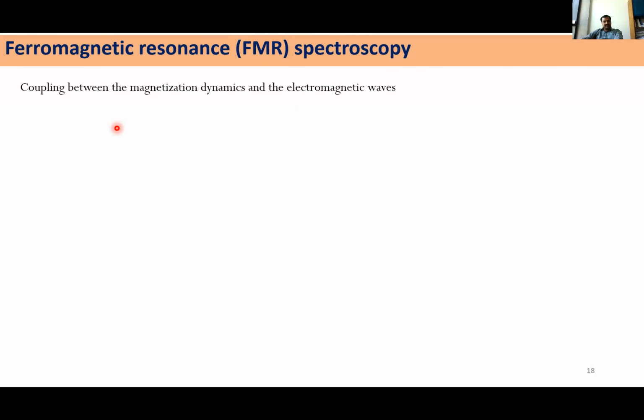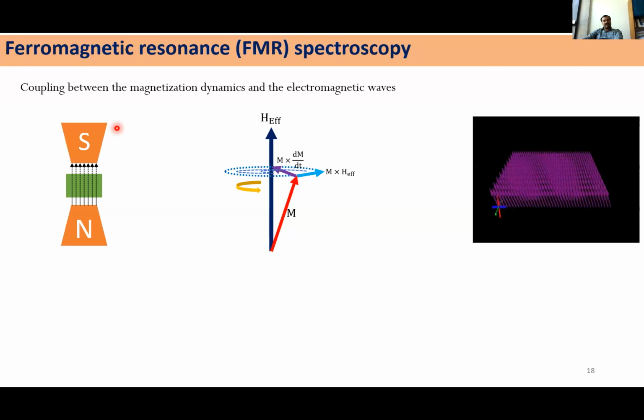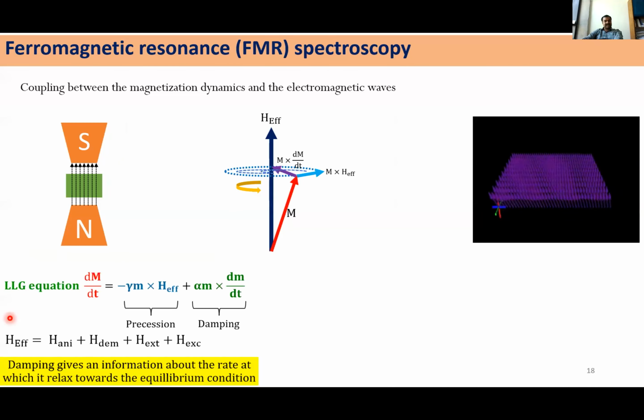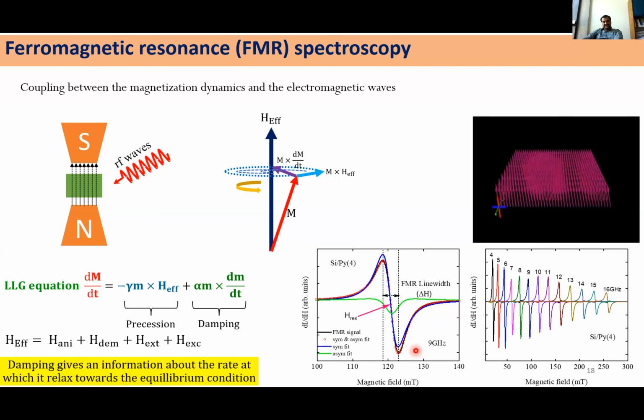So the introduction is already given by Professor Subhankar, so I'll quickly go. Basically, ferromagnetic resonance helps us find out the magnetization dynamics, and it works based on the Landau-Lifshitz-Gilbert equation, which talks about the magnetization precession around the effective magnetic field. So what we are going to do is apply an external RF signal, right? And whenever the frequency of the magnetization precession is equal to the external RF, there is going to be absorption. And that absorption can be seen as a signal in the intensity as a function of the magnetic field. Basically, the first term in the Landau-Lifshitz-Gilbert equation talks about the precession.